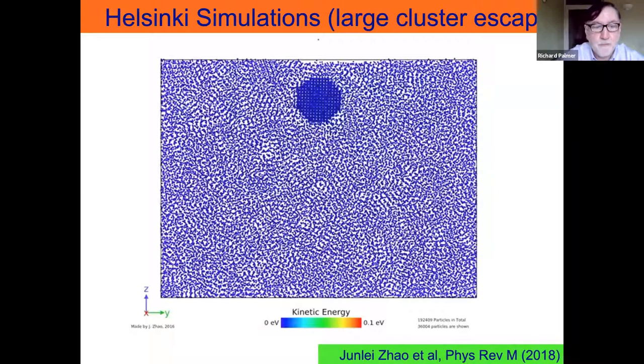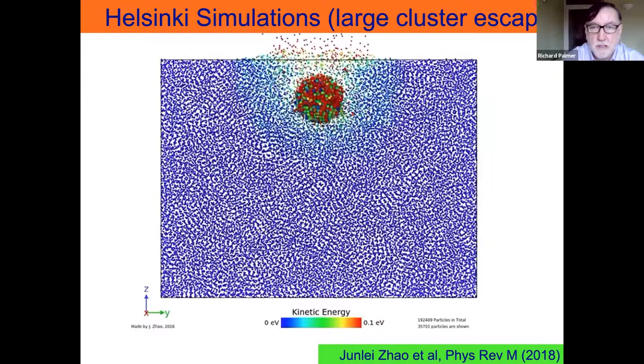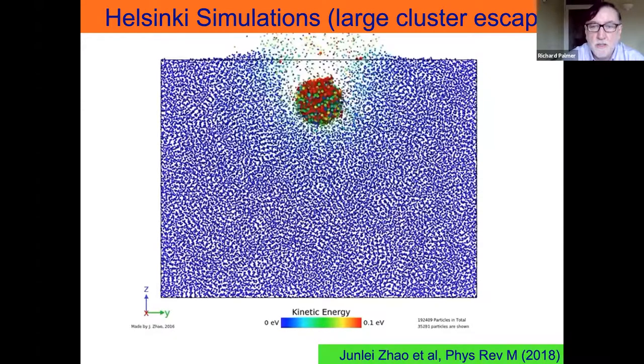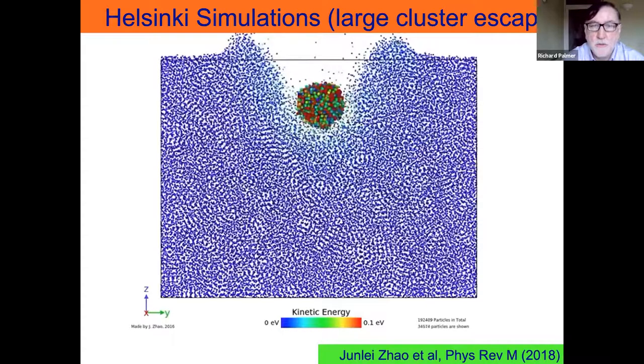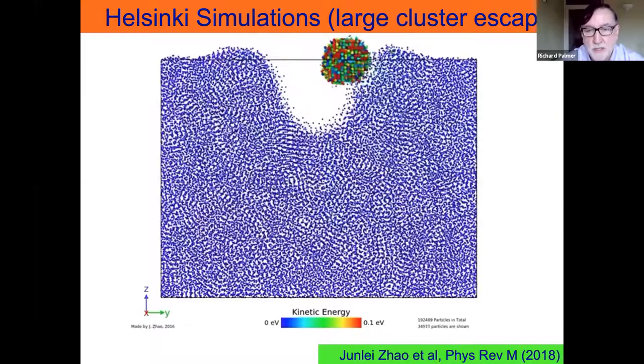I want to show a little video from the Helsinki group of how a nanoparticle already grown in the matrix can be sputtered out to join the beam. An ion has come in and hits the nanoparticle, making it hot as shown by the color. The heat is transferred into the matrix; the argon matrix starts to sublime, and the nanoparticle sees an asymmetrical environment. It is accelerated first down, then bounces off and out it goes to become part of the beam. It was not obvious at the beginning that you could remove nanoparticles like this from the matrix, but that seems to be part of the process, and the simulations are quite revealing.